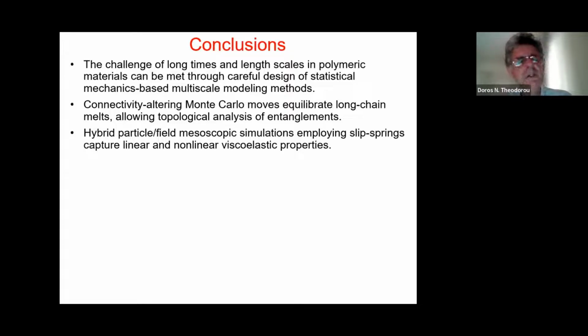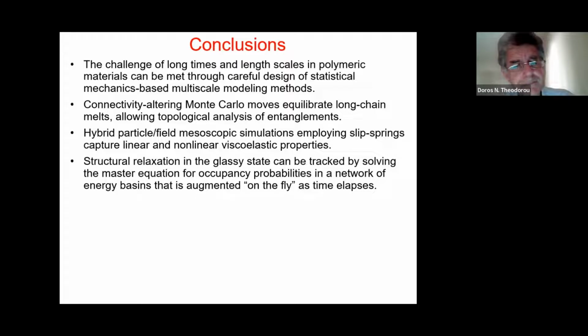You can capture zero shear viscosity, it can capture shear thinning, first and second normal stress differences, G prime and G double prime, and it can also show you what happens in the chains, what is responsible in terms of the long-range conformational properties and orientation of these chains for this complex nonlinear viscoelastic behavior of polymers.